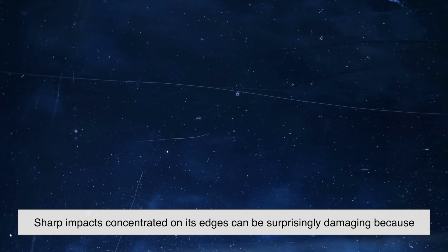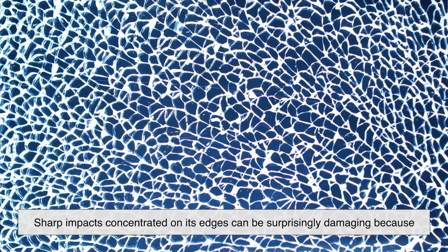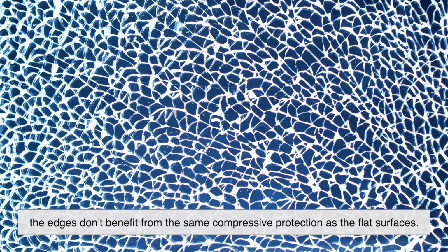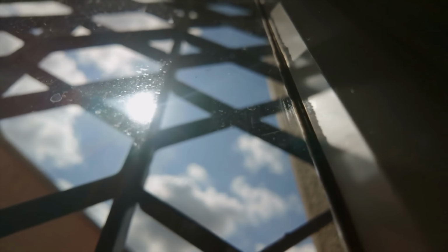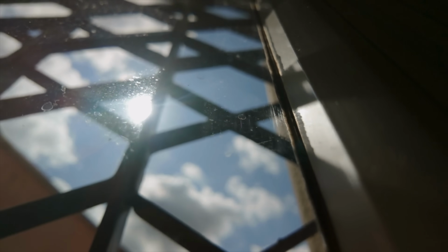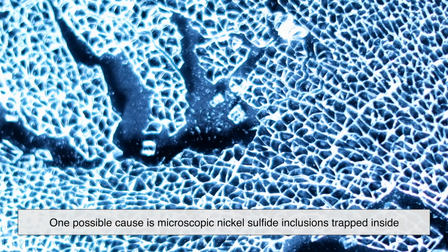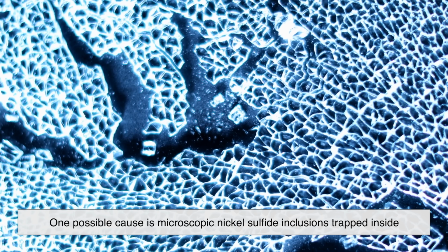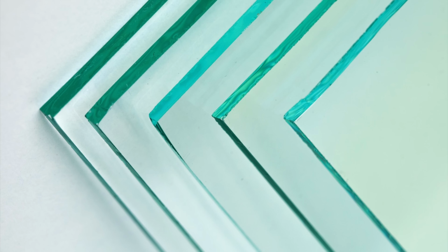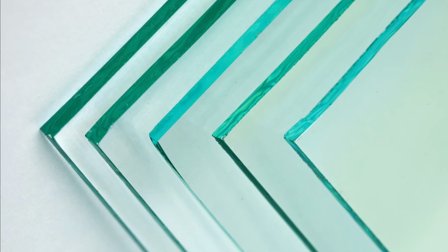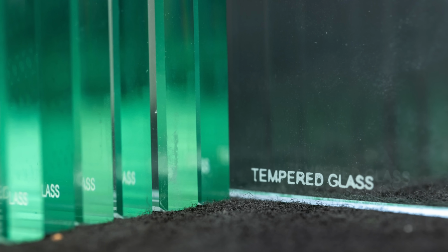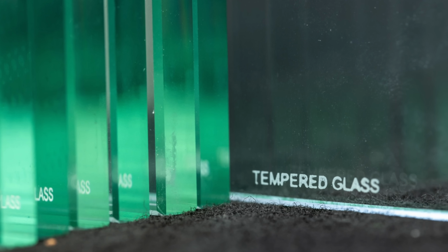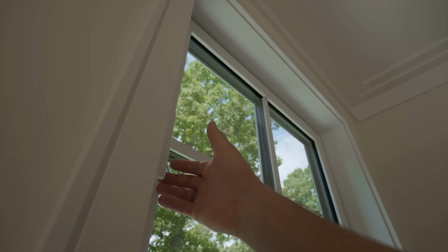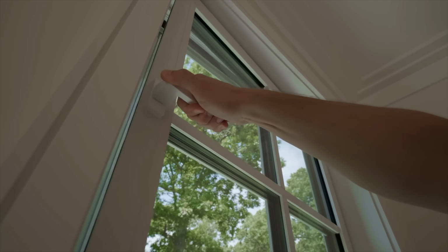Despite its strength, tempered glass isn't indestructible. Sharp impacts concentrated on its edges can be surprisingly damaging, because the edges don't benefit from the same compressive protection as the flat surfaces. Tiny manufacturing imperfections can also occasionally lead to an extremely rare phenomenon called spontaneous breakage. One possible cause is microscopic nickel sulfide inclusions trapped inside the glass during production. Over many years, these inclusions can slowly change size and create enough stress to trigger unexpected failure. Modern quality control greatly reduces this risk, making such incidents uncommon. Because of its internal stresses, tempered glass also can't be repaired once damaged. If it chips or cracks, the entire panel usually needs replacing.